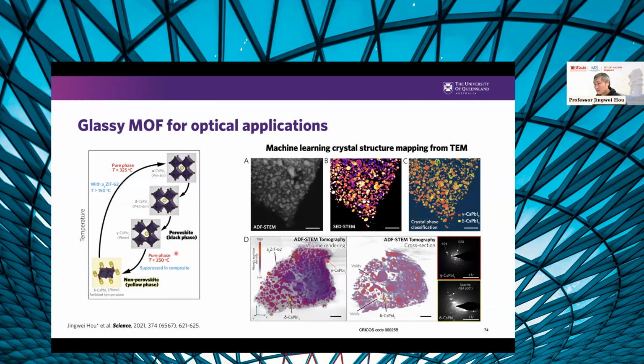The first thing that came into my mind is whether we can design a MOF glass that can freeze the crystal phase above 250 degrees before it goes back to the non-perovskite unusable phase. We can freeze it at the high temperature phase, about 300 degrees. Freezing at 300 degrees is not really sensible, but that's what we actually did. We designed the MOF glass with a phase transition temperature above this temperature, and we can put it together with the perovskite, and that allows us to freeze the perovskite phase at around 325 degrees.